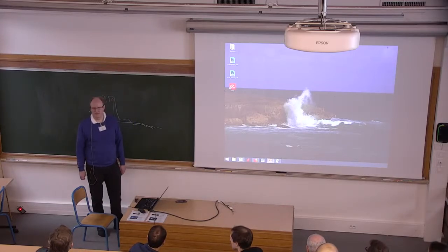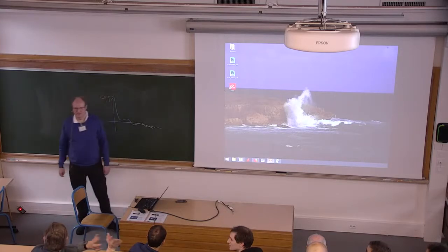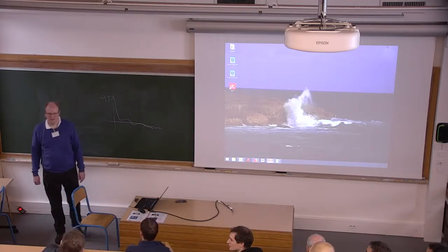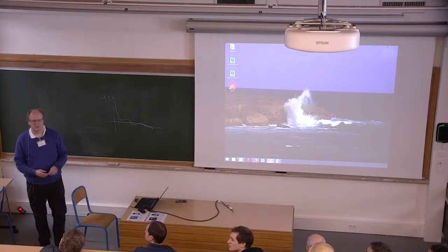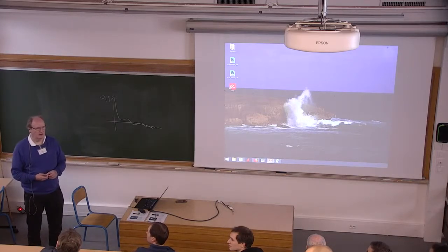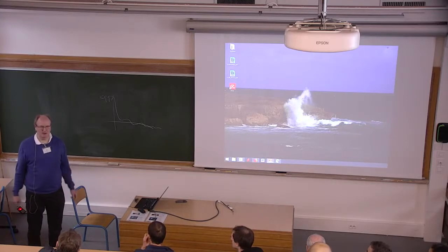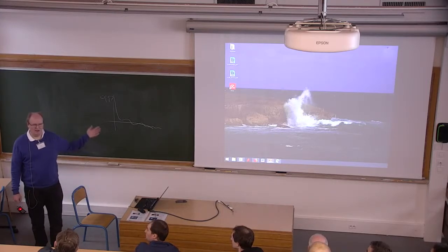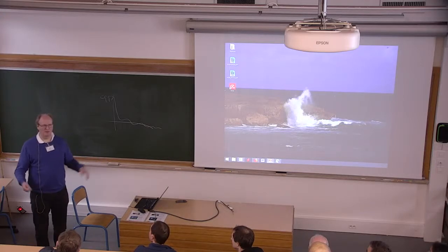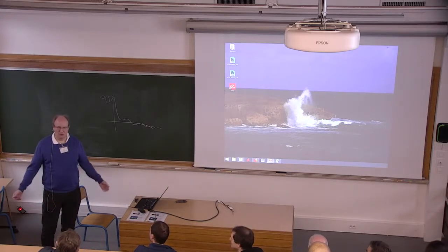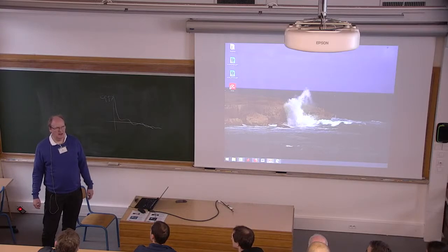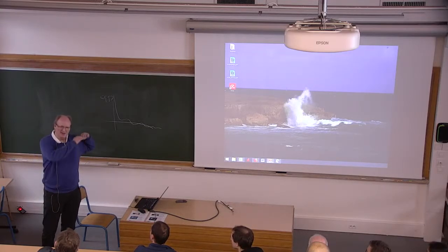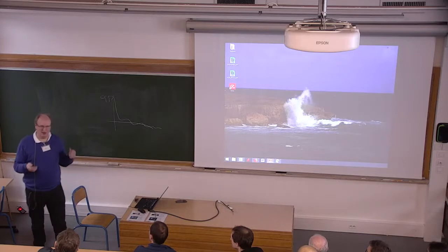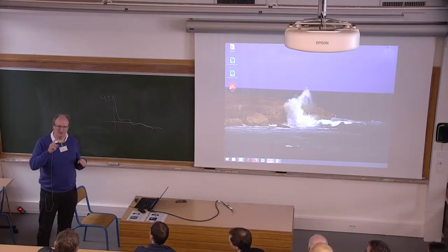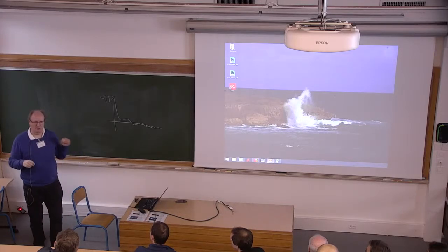Last question, please. My question was basically very related to what that discussion is about. If these structures were directly on the GGG, how would they compare in quality? So we have made nanostructures directly on GGG, because obviously if you can do lift off for bridges, you can also make small structures, and there we also get the damping, so the frequency dependence also corresponds to 2 times 10 to the minus 4. Even for an array, we see 2 times 10 to the minus 4. However, the line width that we see is not as narrow as for these ones.